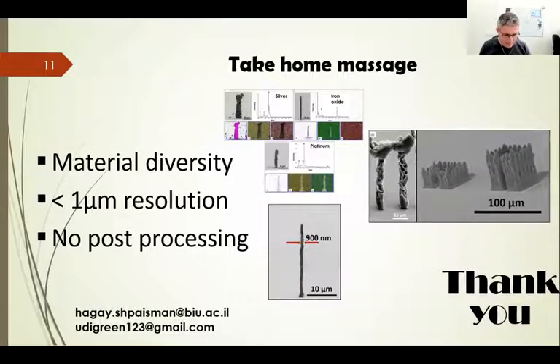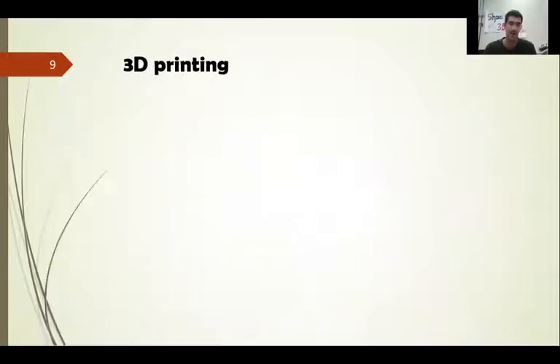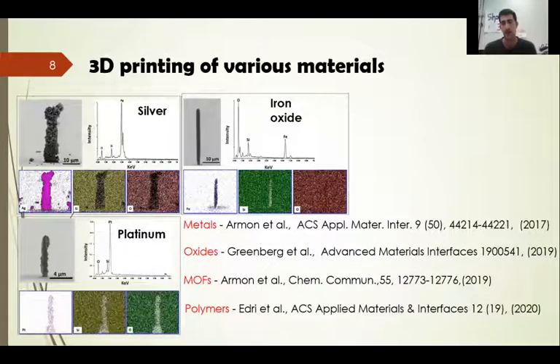When you presented several examples of using salts, but when you talk about polymers, then what is the process? That's probably different. In the case of polymer, we printed a polyaniline, and this is a little different process, but in this case, we start with a resin, and in this process, we made some polymerization of this polymer, or collection of the oligomers into a structure by the microbubble.